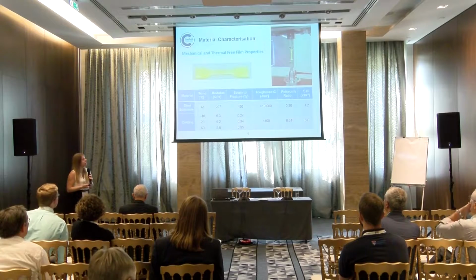So just a little bit about the material characterization. I was able to characterize the material's mechanical and thermal properties using free film standalone samples. The modulus and strain to failure were identified using a tensile test to failure, fracture toughness using a double-edged notch tensile specimen, and coefficient of thermal expansion using thermomechanical analyzer methods.